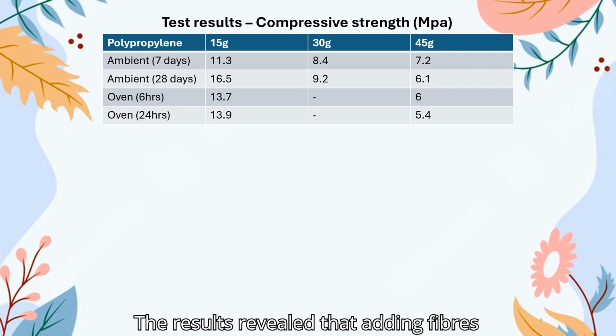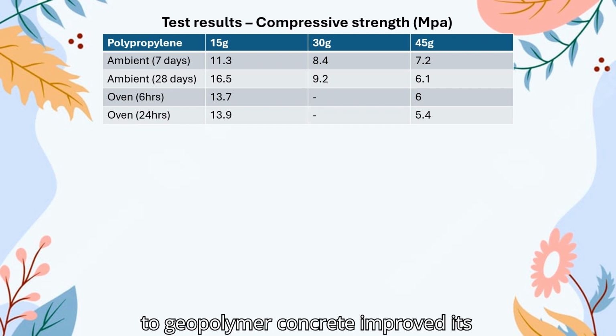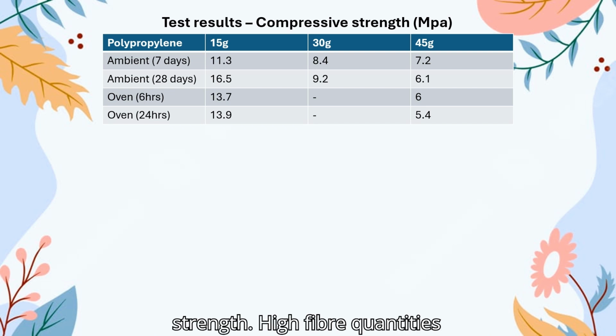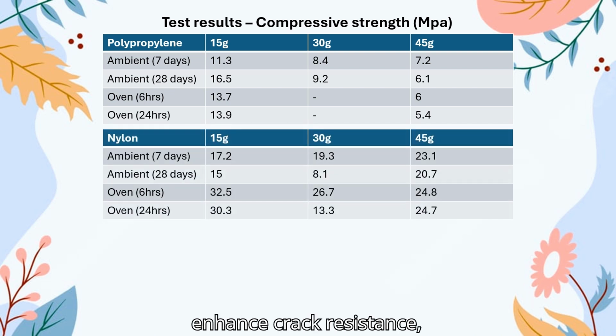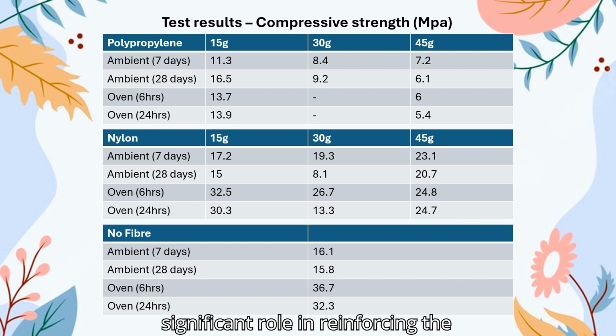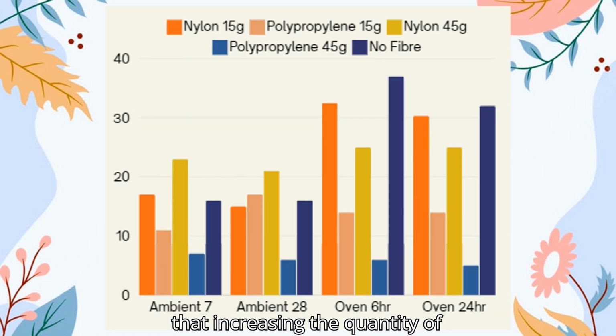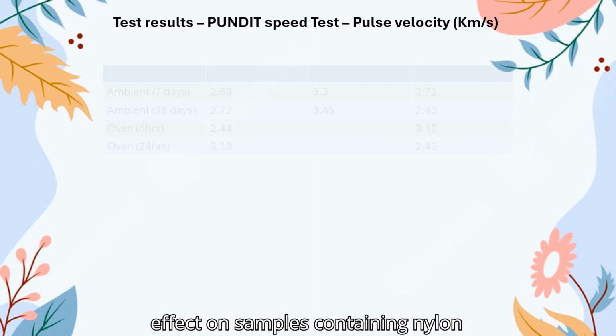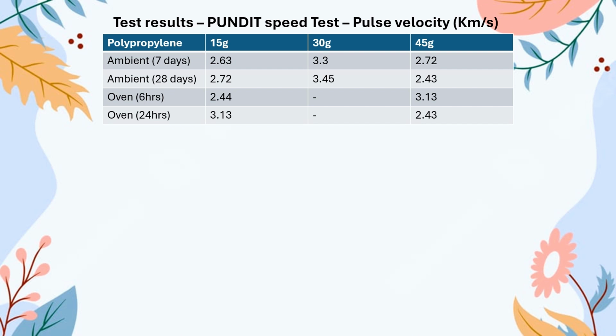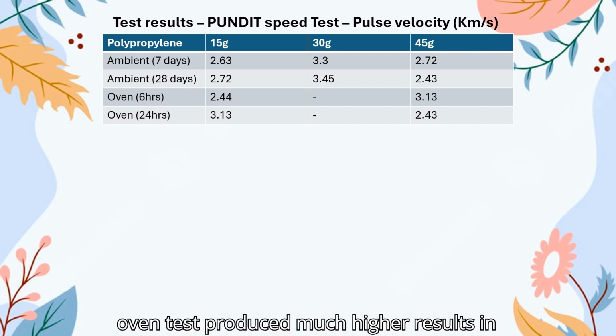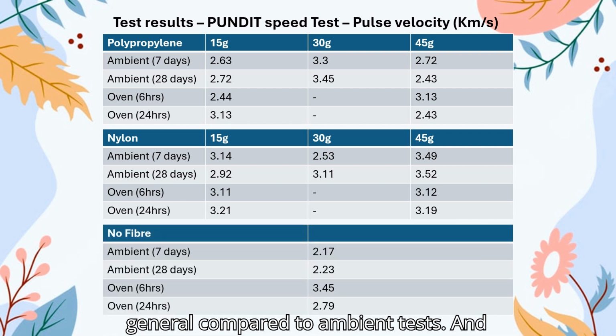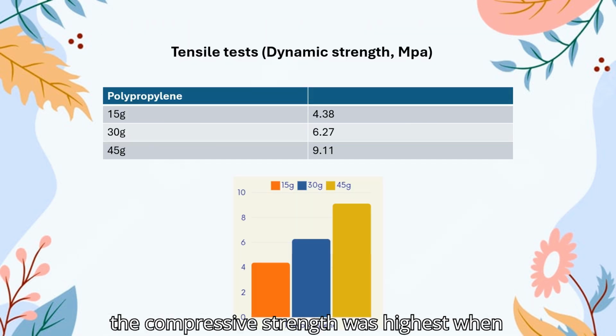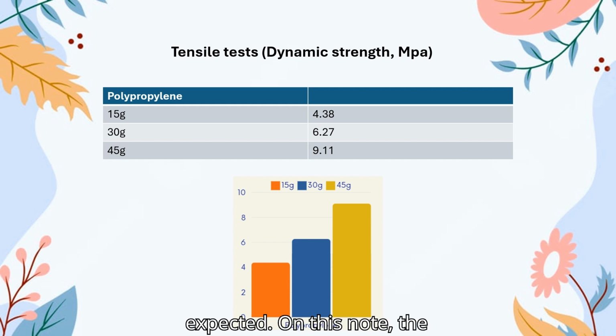The results revealed that adding fibers to geopolymer concrete improved its mechanical properties, especially tensile strength. High fiber quantities enhance crack resistance, indicating that fibers play a significant role in reinforcing the material. Results also show that increasing the quantity of polypropylene fiber resulted in a decrease in compressive strength. However, surprisingly, it had the opposite effect on samples containing nylon fibers in ambient conditions. Oven tests produced much higher results in general compared to ambient tests, and the compressive strength was highest when no fibers were added to the mix, which is expected.